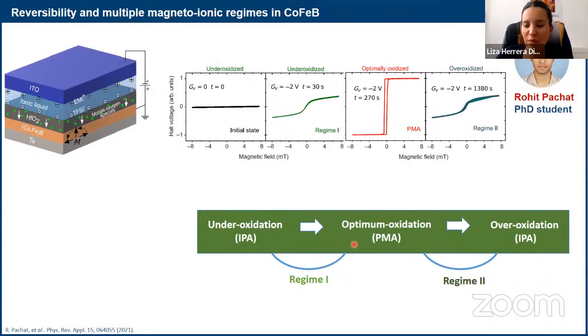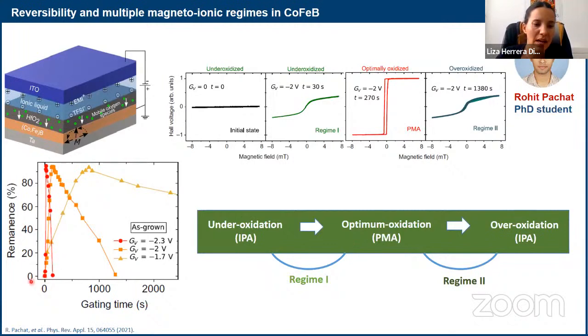So then we define these different regimes, and you can see here that, as a function of the gating time, you can go up from 0 remanence to 100% remanence in the PMA state, and then back to 0 remanence. And this is, of course, faster if you use a higher gate voltage. But you can already see that the branches going up and the branches going down do not really have the same slope. So you can really have a hint that things are not quite the same from under-oxidized to PMA and from PMA to over-oxidized.